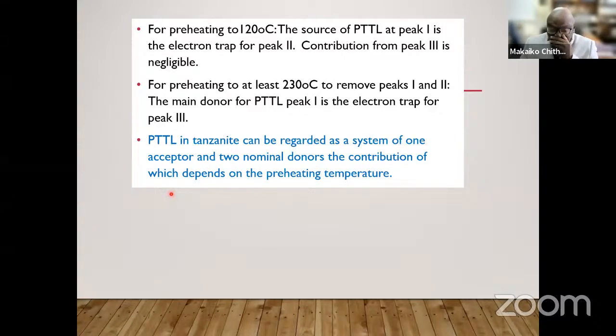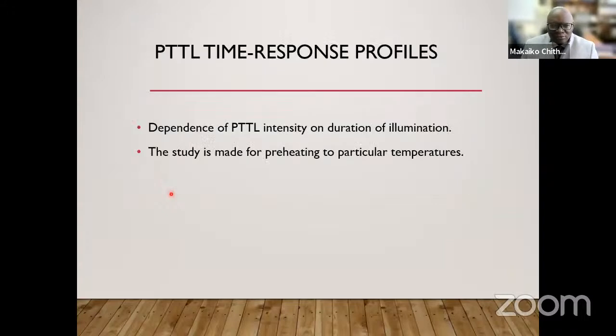Now, remember at first I said you want to analyze the phototransfer as a system of an acceptor and donors. So we can say that the phototransfer in tanzanite can be regarded as a system of one acceptor and 2 nominal donors. But the contribution of those nominal donors actually depends on the preheating temperature. And that was demonstrated in my last graph. So this will give us a means or information to analyze the time response profiles, or the dependence of PTL intensity on duration of illumination.